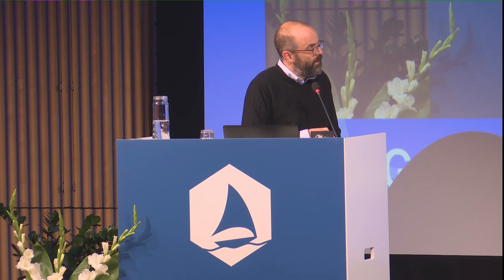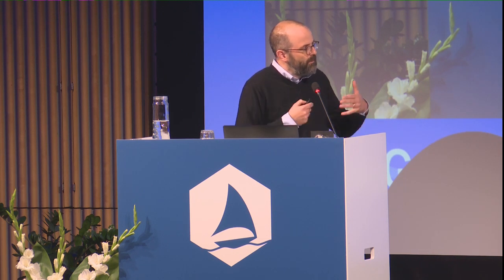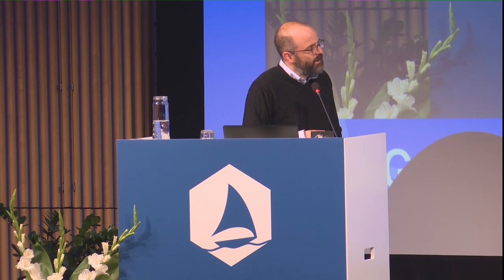So we can do this experiment. Here's a cartoon image of how this looks. Here's my top boron nitride layer, and the arrow is just meant to indicate the crystal direction of the boron nitride and the graphene in this case. Here again is a resistance measured versus density, and I'm starting off in some configuration where the top layer is in some arbitrary alignment, so it's neither 0 nor 60, but remember that the bottom graphene layer is aligned to the bottom BN. So this is what that resistance trace would look like. I have a strong peak at the charge neutrality point, and I have a strong peak at the satellite point. This peak in this case is coming from the fact that this graphene layer is aligned to the bottom BN.